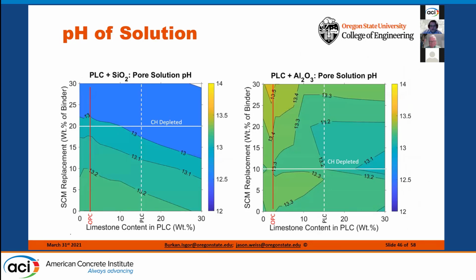We can calculate the amount of calcium hydroxide in the system. So we can show you that calcium hydroxide is depleted when you get to a silica system of above about 20%. We can see that that's also going to happen in the alumina system. We can see what happens to the pH of the pore solution. So this would have impacts on things like corrosion resistance or ASR.